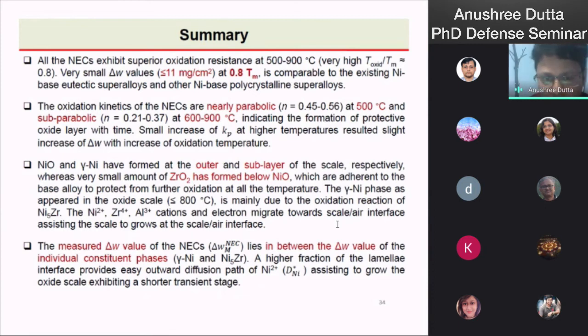NiO and gamma nickel have formed at the outer and sub-layer of the oxide scale respectively, whereas a very small amount of zirconium oxide has formed below the NiO, which is adherent with the base alloy and protects the alloy from further oxidation. The gamma nickel phase appearing in the oxide scale is mainly due to the oxidation reaction of Ni5Zr. The cations Ni2+, Zr4+ and Al3+ and electrons migrate towards the scale-air interface, assisting the scale growth. The measured delta W mass gain of the NECs is in between the delta W values of the individual constituent phases. A higher fraction of lamellar interface provides an easy outward diffusion path, assisting growth of the oxide scale and exhibiting a shorter